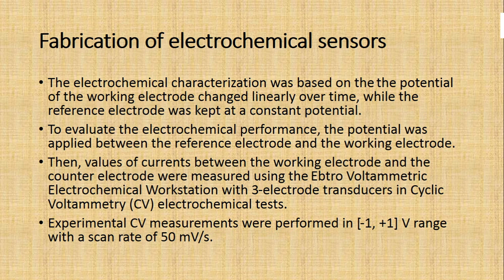The potential of the working electrode was changed linearly over time. The reference electrode was kept at a constant potential. Using three-electrode transducers in cyclic voltammetric mode, the current values between working electrode and counter electrode were measured. The range was -1 to +1 volt and scan rate was 50 millivolts per second.